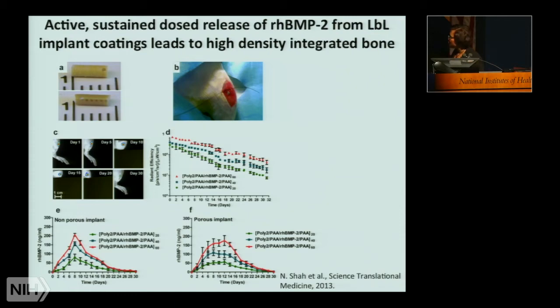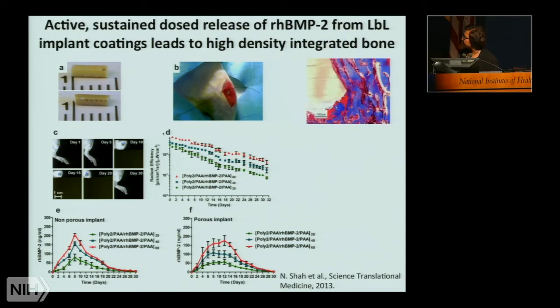You can see over a period of 30 days for the smooth versus the porous or roughened implant, that we can get a more extended or sustained release when we have this texture on the surface or roughening. But what's also interesting is that at any given time, the concentrations don't exceed 200 nanograms per milliliter. And we were talking about the relevance of being able to control the amount of BMP2 released. Here we're getting enough BMP2 in the region to make a difference physiologically without creating enough of a sink of BMP2 to flood the bloodstream with the growth factor.